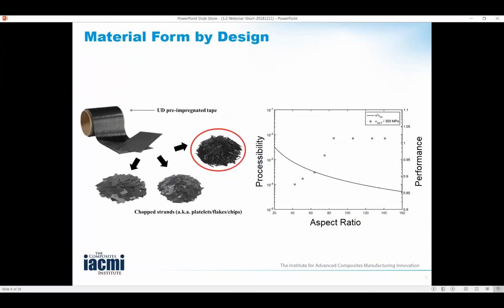Your first question after you've made the pre-preg tape and you've set your fiber volume fraction is, what kind of a platelet should I make? And you can see three different options shown here. We've developed models to understand the influence of the aspect ratio, which in this case is the length to thickness ratio of a platelet, on both the processability and the performance. And you can see that as you increase aspect ratio, you increase performance to a point after which performance asymptotes. However, increasing aspect ratio also decreases processability, as you might intuitively imagine.